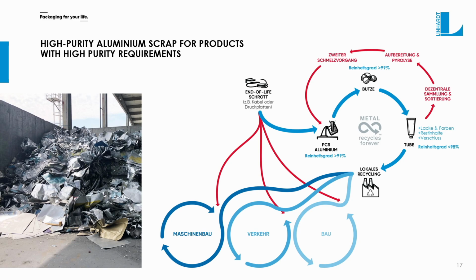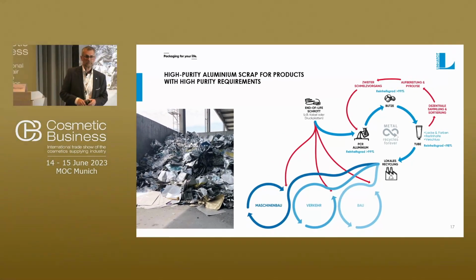The second aspect, instead of using the yellow bag where you have different alloys and where the material, from our point of view, requires significant pyrolysis, high energy input for actually making the material suitable, we could use lithographic plates or cable wire, for example, because they offer a significant degree of purity, 99.1 to 99.4%, and you can see in the picture here, this picture was taken at our material suppliers. This is the heap of scrap, and this is how you put it in the melting furnace. So the scrap gets melted directly, and the molten material will then immediately be passed on to the plant where our materials are produced at.